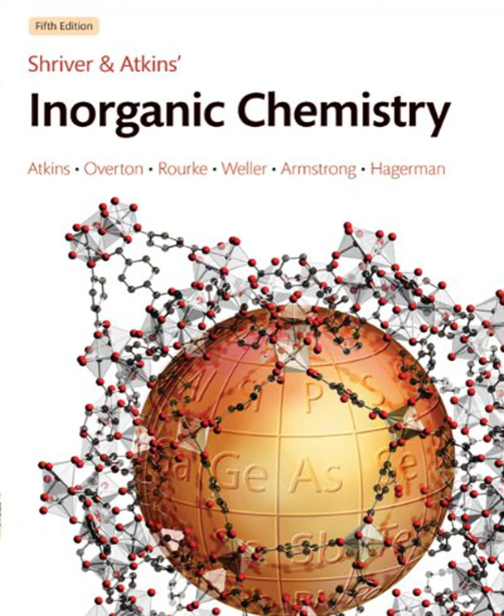Take spinel structures, AB2O4. Normally you'd expect ions to go into sites based on size and charge. But say you have Ni2+, which has a strong LFSE preference for octahedral sites, and Fe3+, which doesn't really care, zero LFSE. The Ni2+ will grab those preferred octahedral sites, even if it means pushing the Fe3+ ions into the tetrahedral sites they might not otherwise occupy. This creates an inverse spinel.